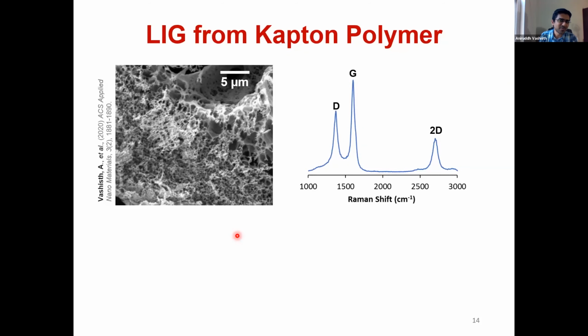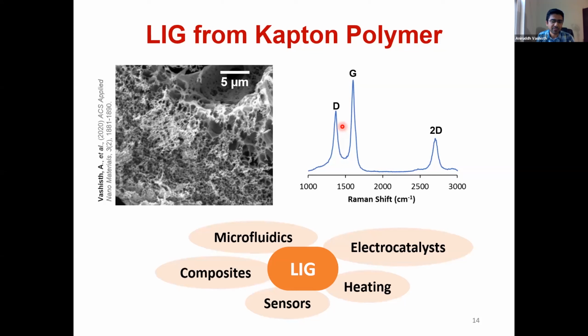So some of the things that we tried. We did some scanning electron microscopy analysis on laser-induced graphene. So here's how laser-induced graphene looks. You can see clearly it's kind of a foamy structure. And if you look at the Raman plots, you can see the G and D peaks, suggesting that there is some ordered graphitic structure there. And LIG has been used for various applications. For example, microfluidics, composites, and it has really good conductivity. So it's been used for sensors, for heating, for analysis, and a couple of other applications as well.